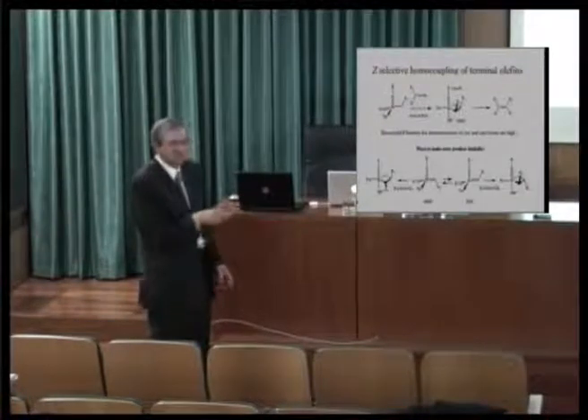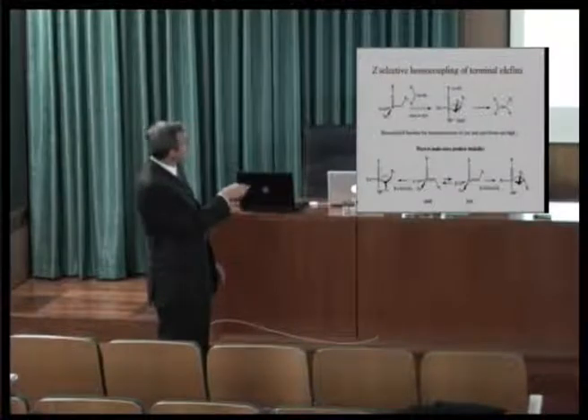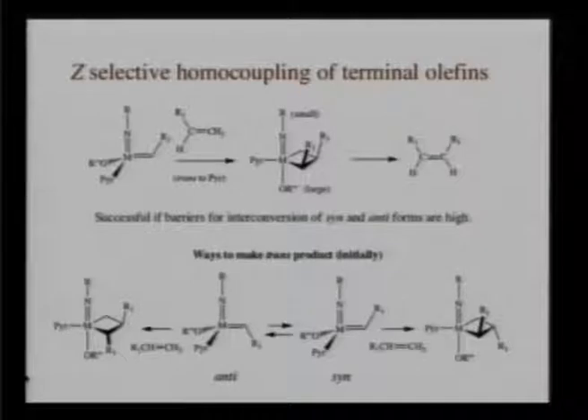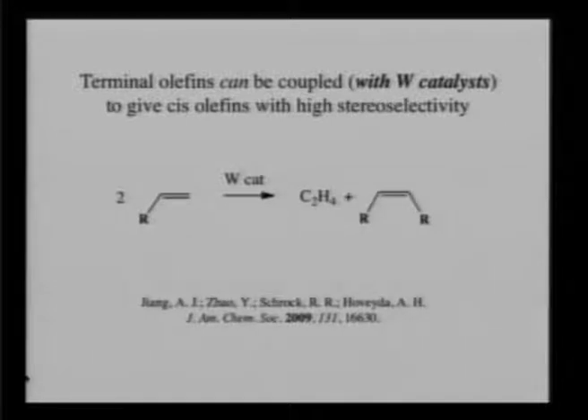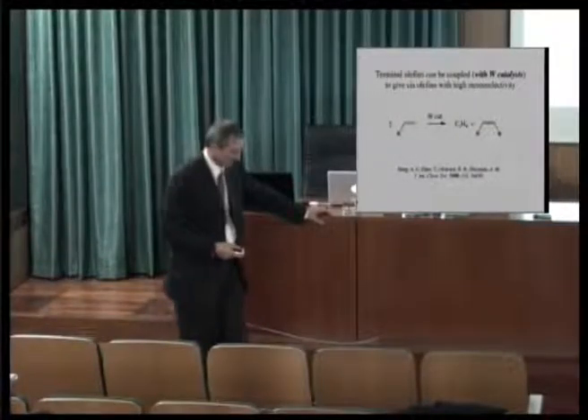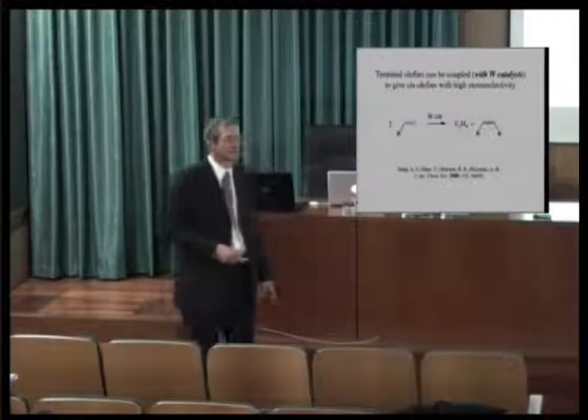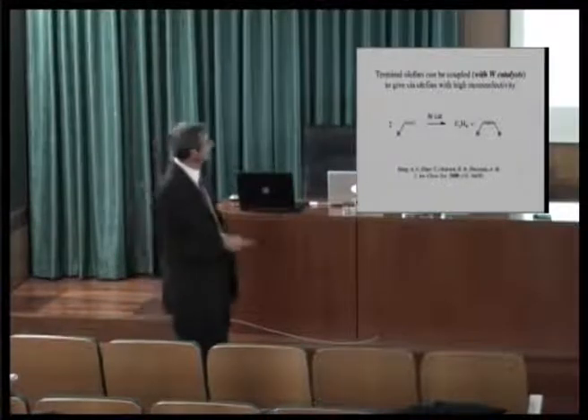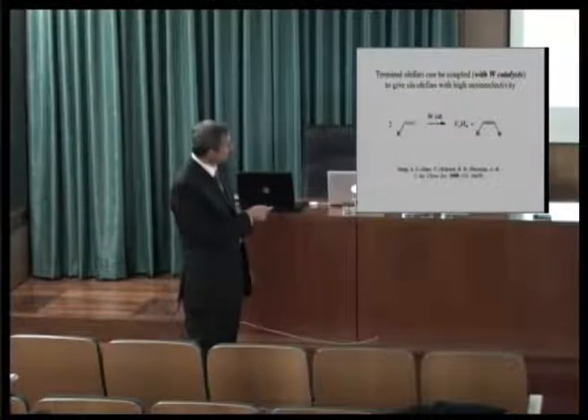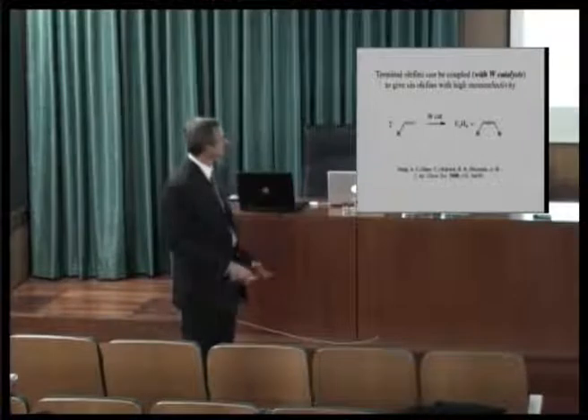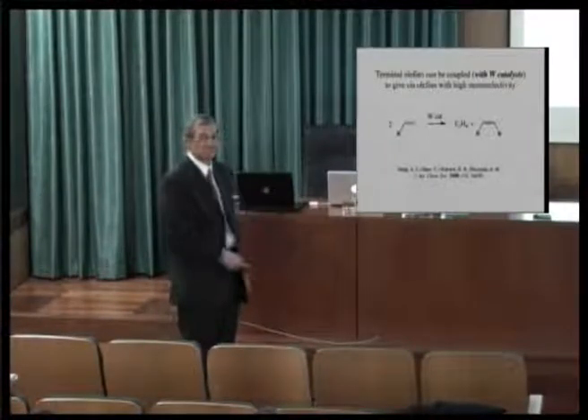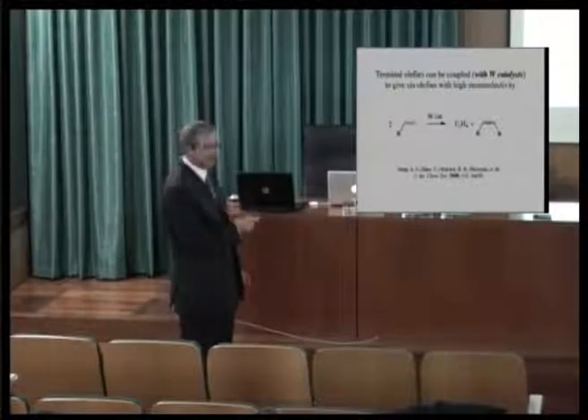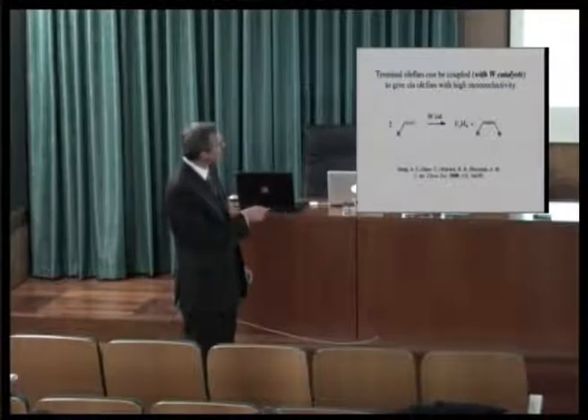There are ways to make trans products. There are several ways. One is simply to not get this intermediate, but the trans one, and then you get the trans product. But we don't think any of these other possible ways of making an olefin, which is trans, take place rapidly. And it turns out that the catalysts that work are tungsten catalysts. The reason happens to be that tungsten, we found out, is much less reactive than molybdenum. Molybdenum is about 5,000 times more reactive than tungsten, and therefore isomerizes the Z product to the thermodynamically more favorable E product. So you get a mixture of about 80% E to 20% Z. But tungsten does not, because it's not active enough. It's active enough to do the coupling, but not active enough to isomerize the product.